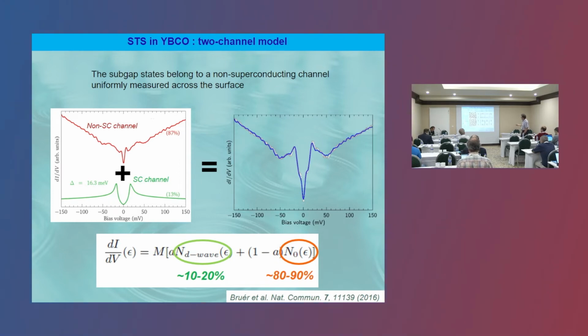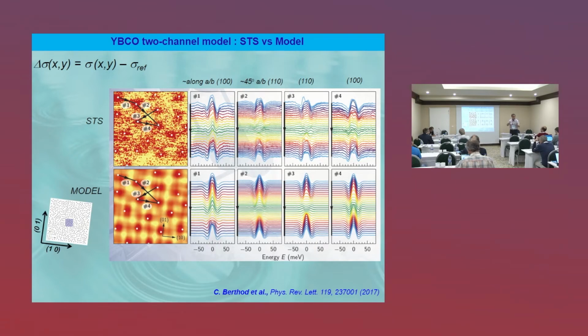I'm skipping the details, but by subtracting a reference spectrum, we get rid of this uniform non-superconducting channel, and we are left with the differential spectra. The top line is the real measurement, and the bottom is the calculation where we took the exact positions of the vortices we acquired. Then, in order to be consistent with the fact that the positions of the vortices influence the spectroscopic signature of all the other vortices, we generated a random distribution of vortex lines around, and this is the calculation. You see that the match between the experiment and the calculation is quite good.